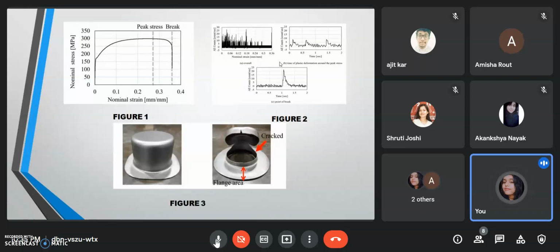AE characteristic in deep drawing test. Figure 3 shows the product of deep drawing. From the comparison of workpieces in figure 3, the flange area of the cracked product is larger than the flange area of the normal product. As a result, it can be confirmed that cracks occurred at the initial stage of the forming. Recognition of deep drawing state by machine learning. As shown above, forming state recognition should be confirmed. Therefore, recognition through machine learning was tested.